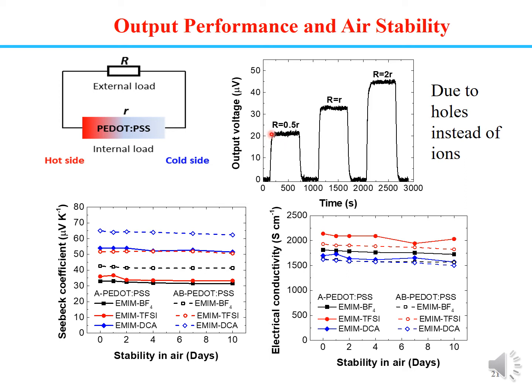If it's ions, the output voltage should decrease with time. We also investigated the stability of PEDOT:PSS with the ionic liquid. Both the Seebeck coefficient and the electric conductivity are quite stable.